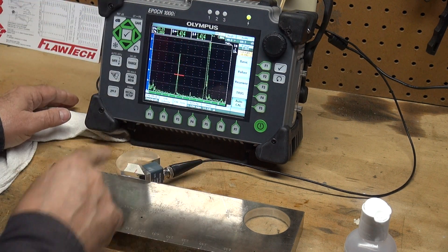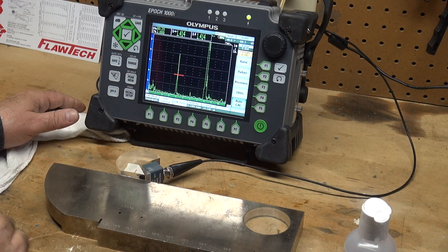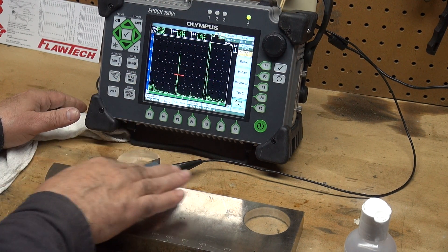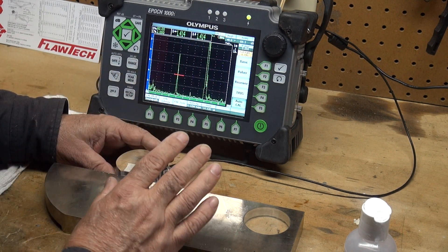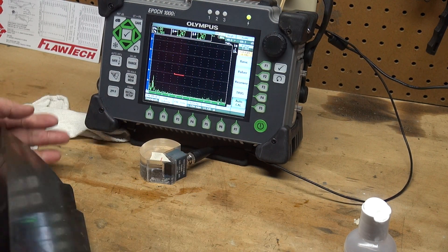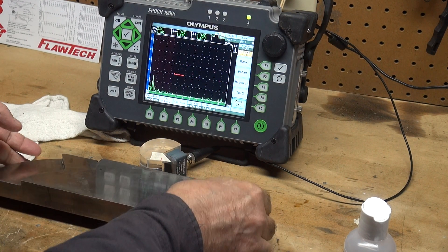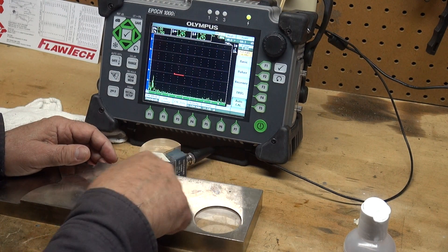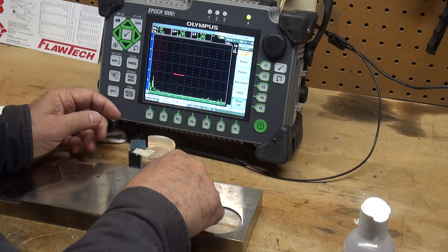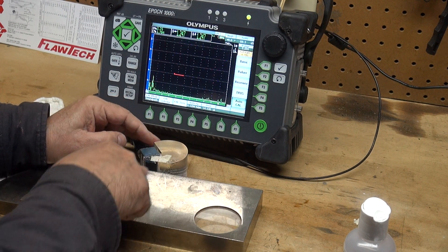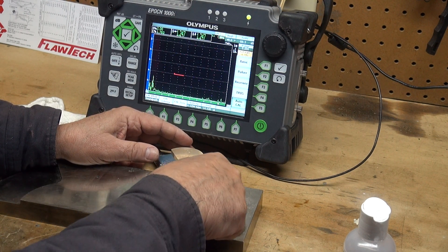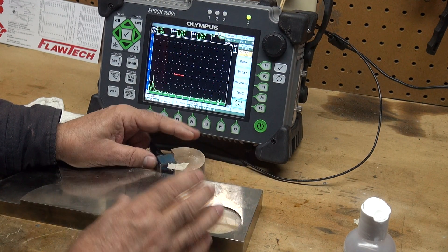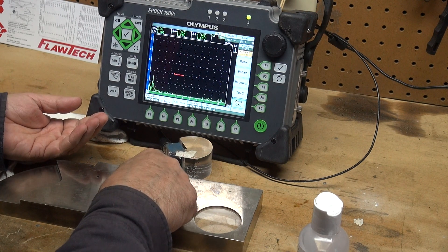The next thing we want to do is see if this wedge is really 45 degrees. Under use it could change the angle slightly, so we always want to measure our real angle. On this IIW type 2 block I have a scale from 30 degrees to 60 degrees. The sound is shooting down at this hole and I'm looking for my maximum sound to come back.